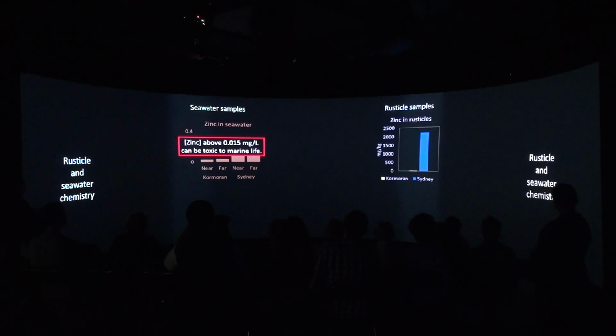So we know that the rusticles were mainly iron oxides, but what else was in the rusticles or around the rusticles in the seawater? We had the seawater samples analyzed, and we found that the seawater samples near the bow of the Sydney had really high concentrations of zinc. And it was above the toxicity levels for these metal or metalloid. So we were also wondering, is this being reflected also in the rusticle chemistry? Yes. Here you can see that the Sydney has much more zinc in the rusticles than the Kormoran.